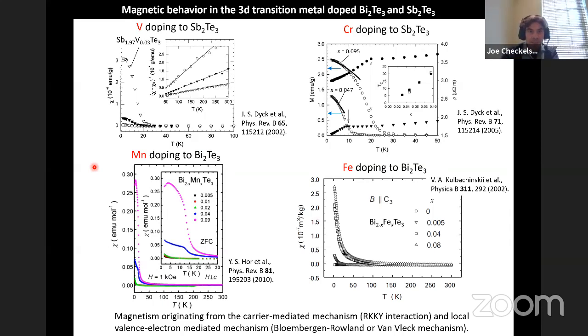So how would you make one of these materials magnetic? It turned out that these kind of workhorse topological materials, whether antimony telluride or bismuth telluride, a lot of them had been explored in the context of magnetism even prior to the understanding that they could have interesting topological phases. And it was in a different and interesting context called dilute magnetic semiconductors. By making these systems magnetic, you take these small gap semiconductors and you just try to force in some transition element using doping.